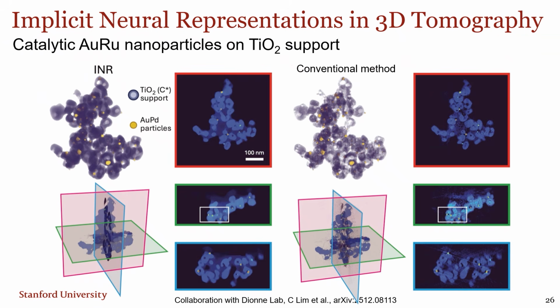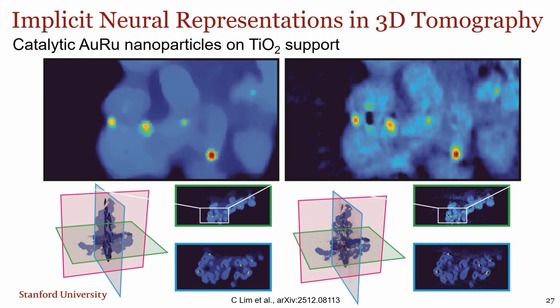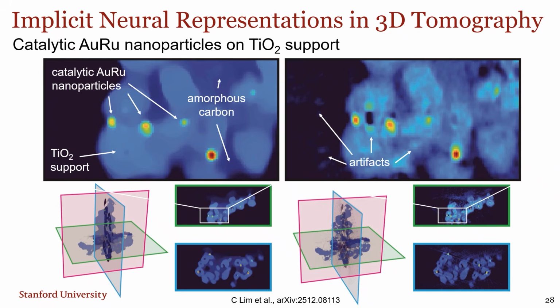But it goes further. If we take this volume and we slice it in different directions here and then zoom in on one of the slices, again, on the left-hand side is the machine learning-driven reconstruction. Right is a more conventional algorithm here. And I just want to highlight the massive difference between the two. When you're studying something like catalysis, it's actually the triple points that are often the most important structural components, where the gas phase can meet the catalytic nanoparticle and the support.